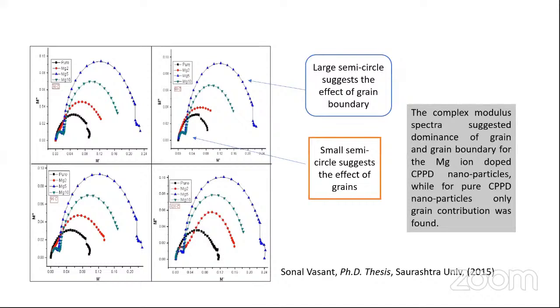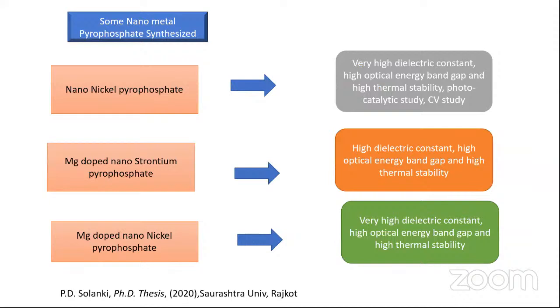Now we come to some of the recent results, but I will not share any diagrams or plots, because these are still in the process of publication. The important finding is that nano nickel pyrophosphate has a very high dielectric constant, in terms of 1000, a high optical energy band gap, high thermal stability, and photocatalytic activity, and it is used as an electrode material for cyclic voltammetry. So for supercapacitor, for photocatalytic applications, and for dielectric material applications, this material is found to be a very superior one.